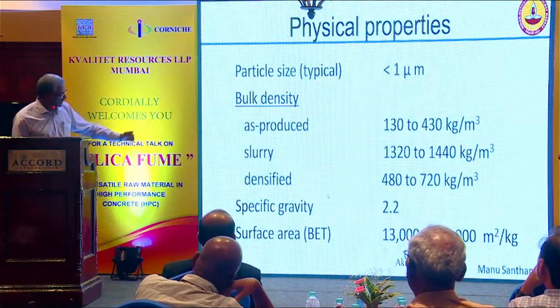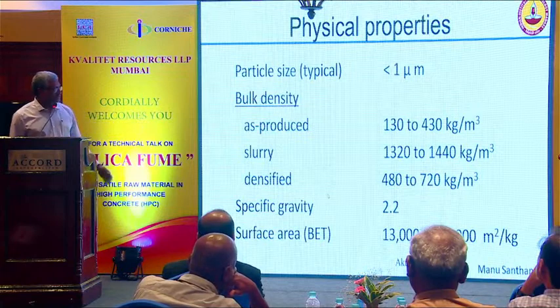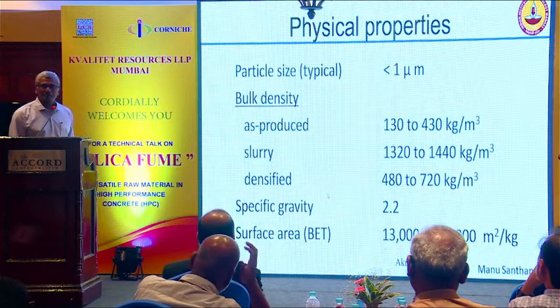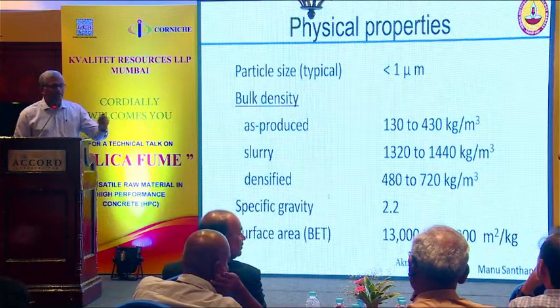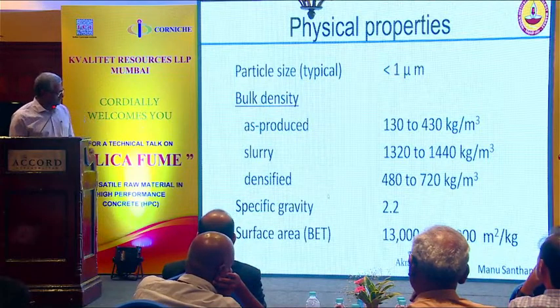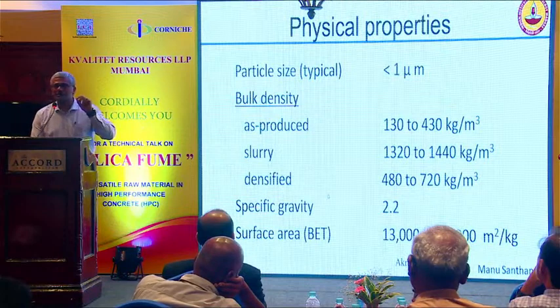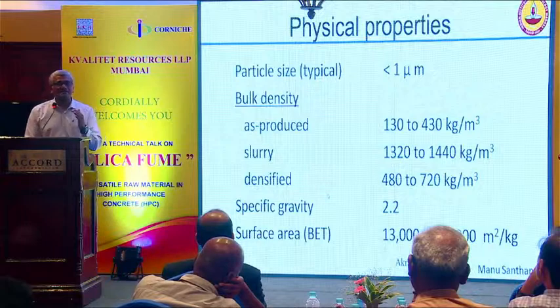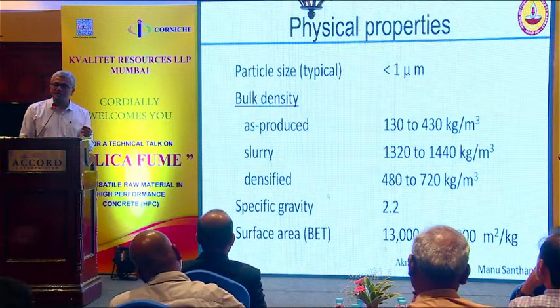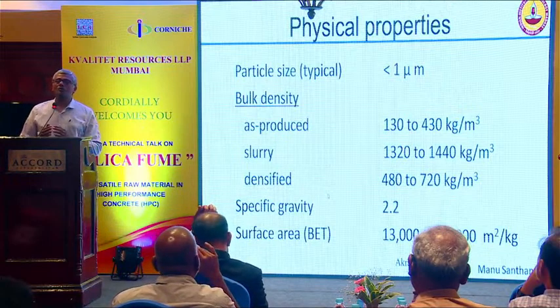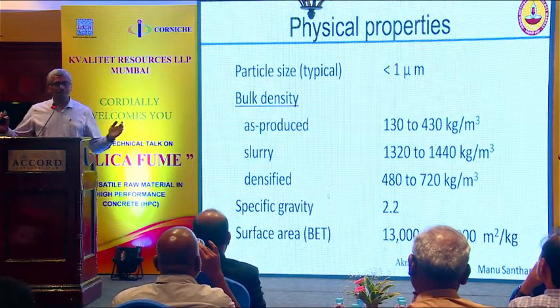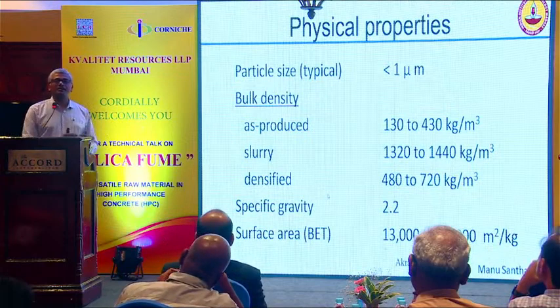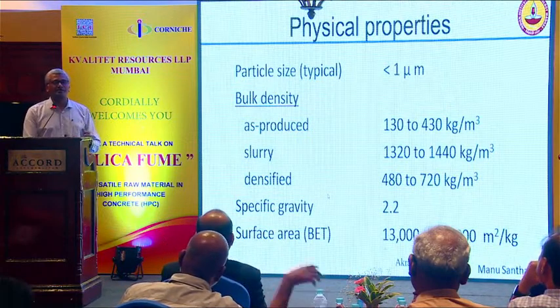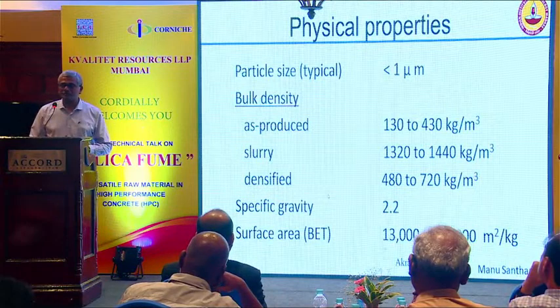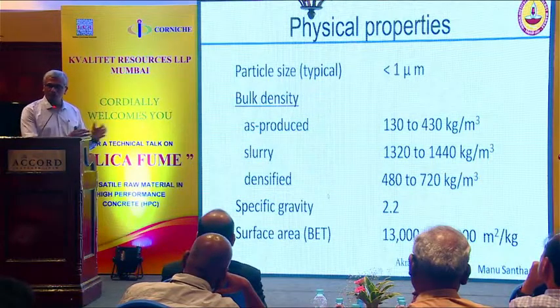I'll show you why we have to densify it to get a density which is around 500 to 700 kilograms per cubic meter. I may be off by some extent. Maybe the lecture by Mr. Hasbi will have the correct numbers. But particle specific gravity of silica fume is about 2.2. Cement, you all know, is about 3.15. So you're replacing cement with a finer material with lower specific gravity, right? So you expect the volume of your paste to go up. You're replacing a denser material by the lighter material. So if you're doing a mass replacement, your volume of paste will go up. Okay? That you have to be sure about when you do the mix design.